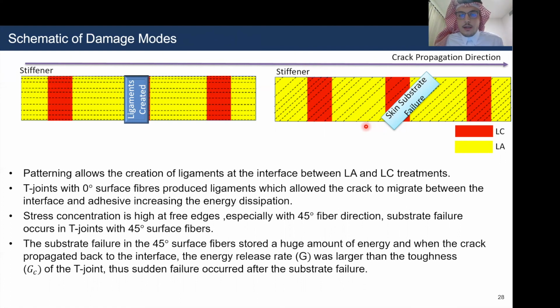And in this case, the 45-degree fiber direction increased the stress concentration at those free edges, and it was really easy to peel or remove the fibers off the skin. This allowed what is known as substrate failure to occur with the 45 degrees. Analyzing the crack, as it entered the skin, it stored a huge amount of energy. The energy release rate of the crack was really large, so that as soon as it exited the substrate, it was larger than the toughness of the T-joint, and this allowed sudden failure to occur.